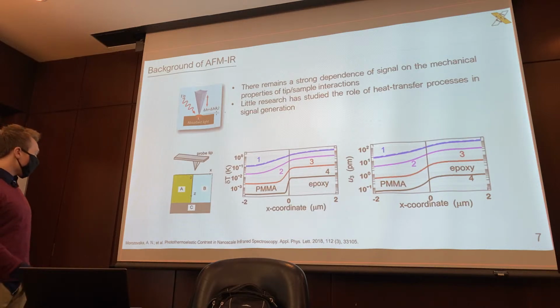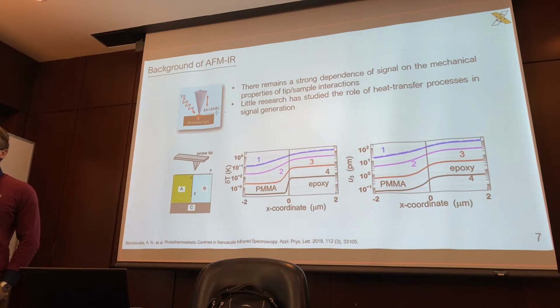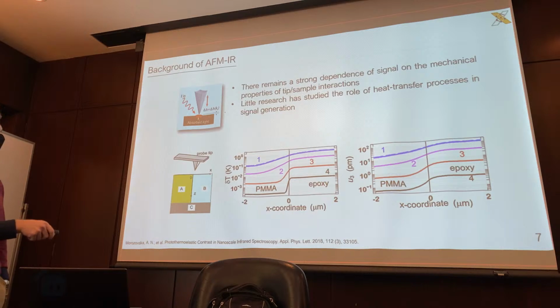A good example that I found was this paper by our friends up at Oak Ridge. So some of this work was done in Poland, actually. Sorry, not Poland, the Ukraine, where they created this sandwich layer of materials where they had PMMA lodged up against a layer of epoxy. And they measured the thermal response of the epoxy, and here we have the change in temperature on the y-axis, and this is the x-coordinate that corresponds to the lateral distance. And on the right-hand side, we have the actual thermal expansion in terms of deflection in picometers, and the x-axis again corresponds to the lateral distance.